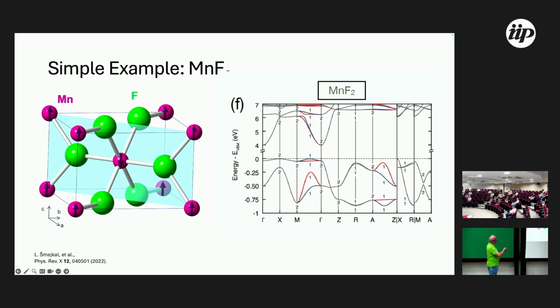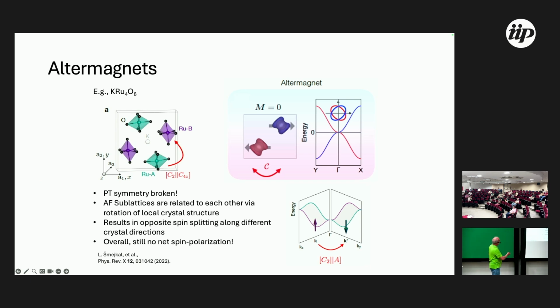But the atoms around the sublattice are rotated. For this sublattice, they're pointing in this direction. For this sublattice, they point 90 degrees rotated. So in that sense, he got it right. The immediate chemical environment is rotated, but the orientation of the local magnetic moments is fixed. So there's a fixed axis. The same here for this material, I think the spin direction is probably along the z-axis, pointing at us. But in the AB plane, you have these rotated octahedra.